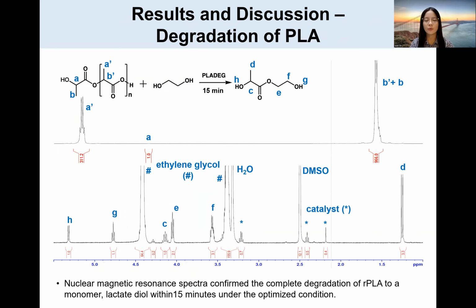So here's how I know that PLA had been completely degraded within 15 minutes. The upper spectrum is the NMR spectrum of the starting material. So by comparing these two NMR spectrums, it's obvious to see that the two peaks located at 1.5 and 5.2 ppm have completely disappeared after 15 minutes. The peaks from lactodiol, as you can see here, can be clearly assigned. That means the degradation is completely successful, reaching an over 99% yield of lactodiol within just 15 minutes.